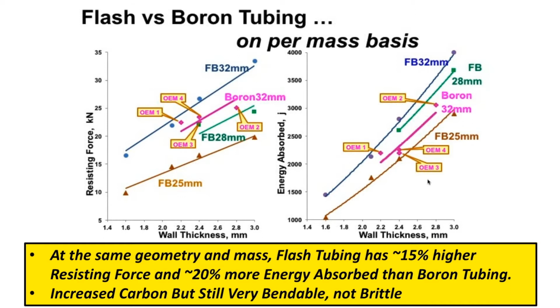Now, some people have said, well, of course it does. You're working with 4130 alloy steel. Boron steels are only typically, you know, 0.22 to 0.25. And my comeback to that statement is that flash bainite has the ability to hold its carbon better than a boron steel does without becoming brittle.